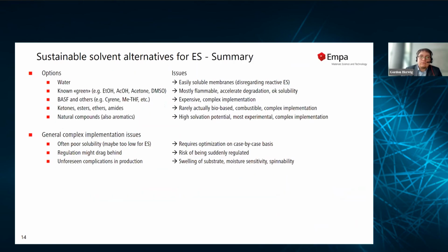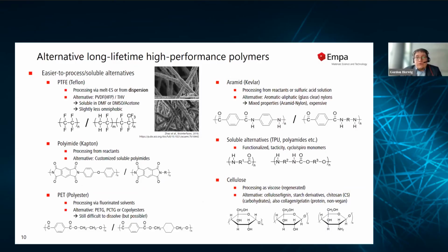And so in these cases, you're using a combination of non-fluorinated surfactants and other polymer carriers, or? For putting them into the organic solution, you don't need any emulsifiers whatsoever, any suspending additives. You can simply add it in there, and simply by the viscosity and by the fact that you have a relatively viscous polymer solution with DMF, you have both the hydrophilicity and hydrophobicity at once, which let's say encapsulates or forms a film around the particles much better. So they don't crash out of solution in the time that we are spinning them at all.